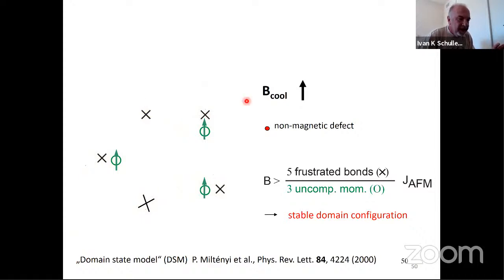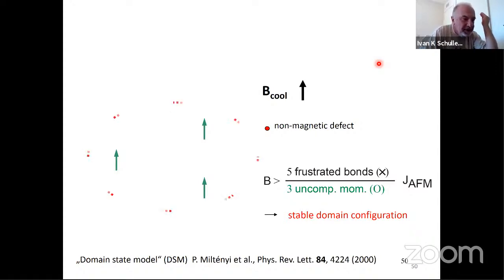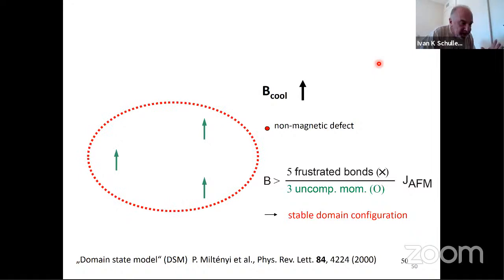The defects are, and now I'm going to eliminate the defects. And the only spins that are left in the antiferromagnet are those green spins. Those are the pinned uncompensated moments. So notice what I'm telling you there, that there is a bunch of spins that are sitting on the crystal structure of the antiferromagnet because of the defects, and they are uncompensated. Then, but there is a background of antiferromagnetism there, okay?